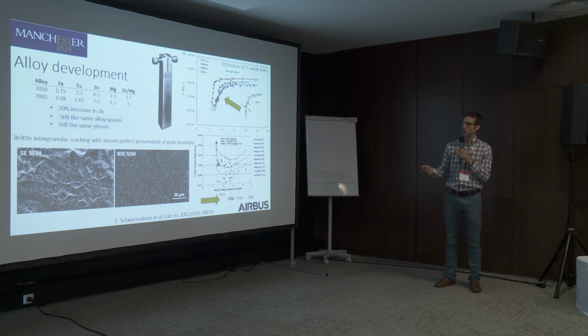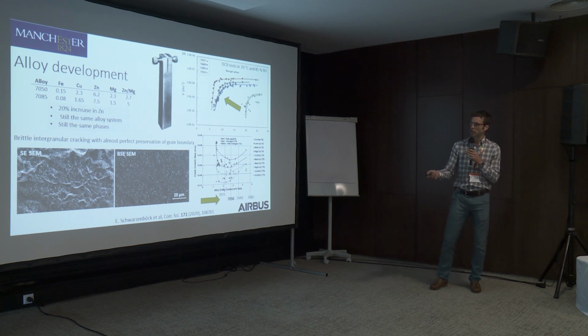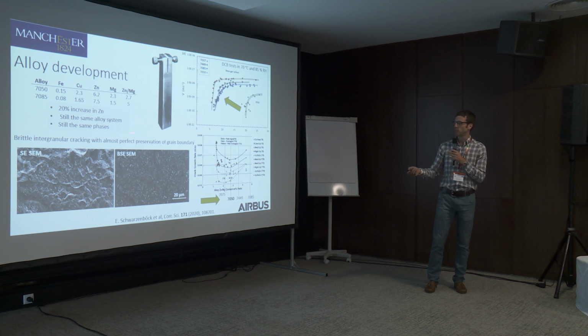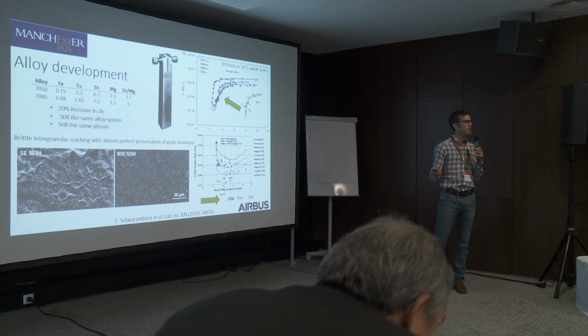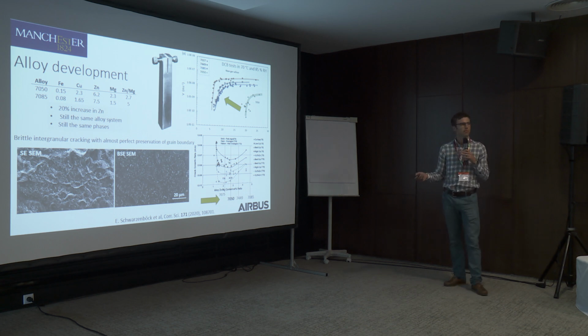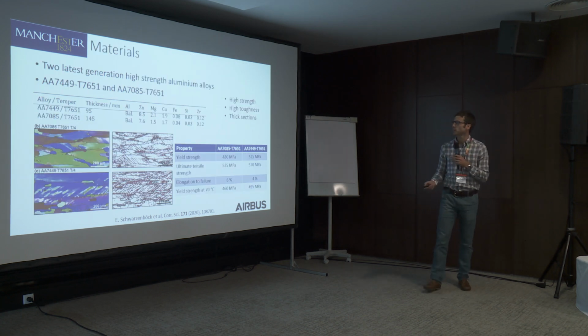And these materials are characterized, like hydrogen embrittlement, as a decohesion mechanism, characterized by these extremely brittle intergranular fracture surfaces. And basically the prevailing trend that takes us from these previous generation materials to the current generation of materials is this changing composition, which is making the materials stronger, and by removing iron and silicon is making them tougher. But we've got increasing levels of zinc, and crucially an increasing zinc to magnesium ratio.